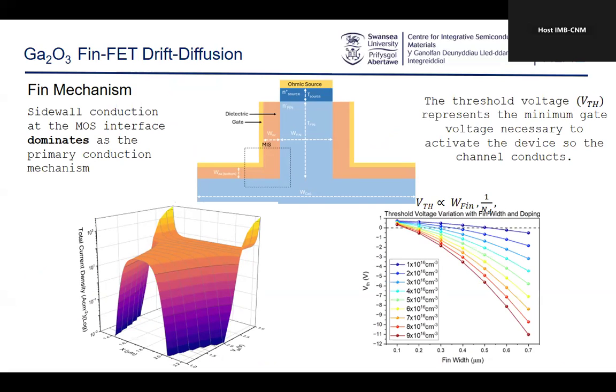As my predecessor said earlier in his excellent talk on gallium oxide, gallium oxide has no P-type material. So again, we're looking at a very similar JFET-type fin structure in gallium oxide. One, because there's no P-type in gallium oxide, so you can't make an enhancement mode device. And two, because we could benefit from a lot of the work we'd already done in silicon carbide and transfer it to gallium oxide. And what the student looked at in this study was